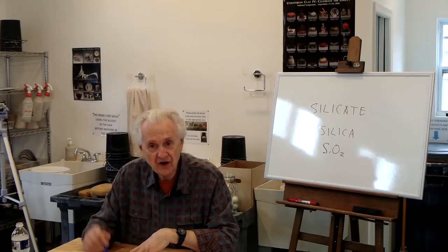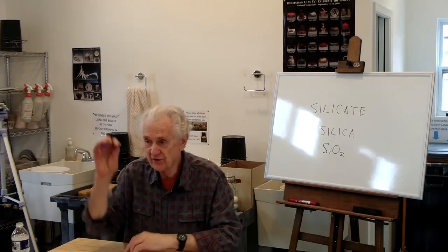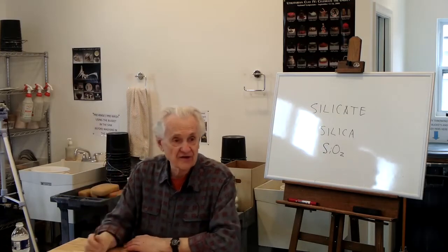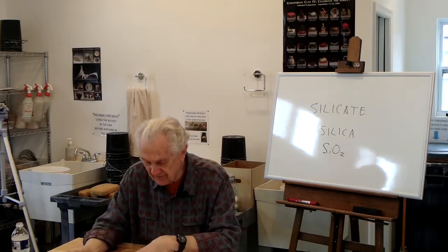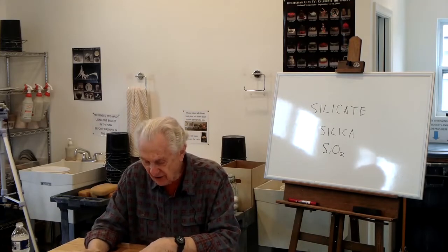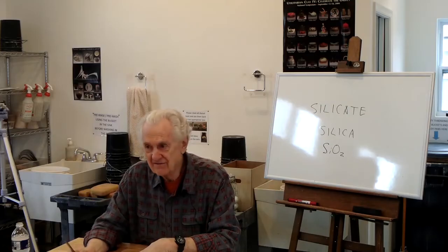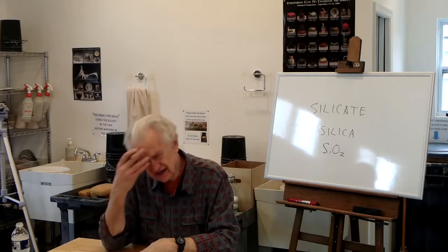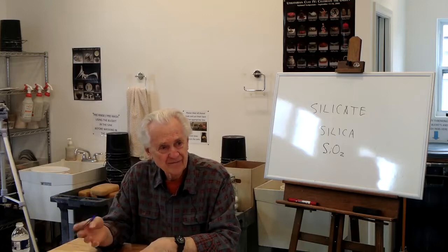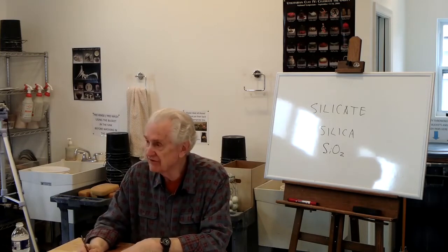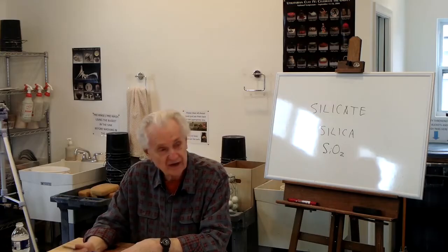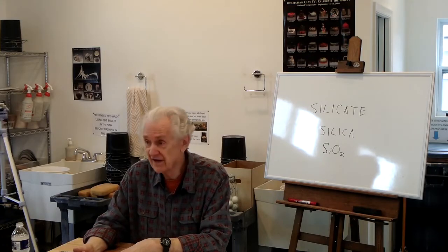So as long as it's on weight, regardless of what those numbers are, I can convert the recipe to weight percent, and then it's a whole lot more useful. Because if I had this recipe where I've got 58.5 parts of whiting, and I wanted to make a 450-gram batch, you go like, how in the world do I do that? Well, if it's percent, it's easy. I multiply 450 grams by 19.7%, and that tells me how much whiting to use. Everybody follow that?